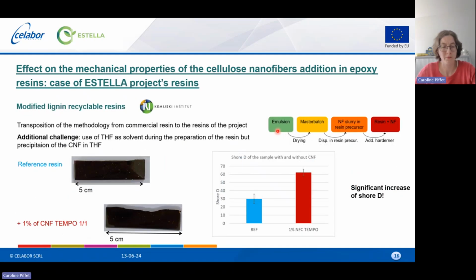Then we transposed the strategy up to the ESTELLA Project resins. So the resin developed by our partner from Kemijski Institute in Slovenia are modified lignin recyclable resins. So we decided to prepare, with the same strategy, an emulsion, a master batch, dispersing this master batch, and adding the hardener.